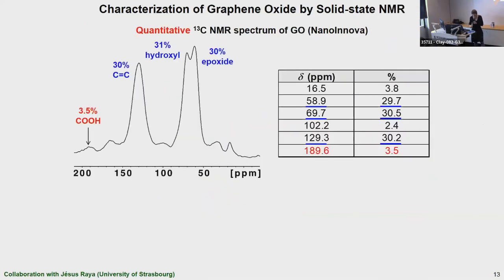We then characterized the graphene oxide by solid state NMR using quantitative carbon-13 NMR. So we could determine that graphene oxide was composed of around 1/3 of epoxides, 1/3 of hydroxyls, and 1/3 of carbon-carbon double bonds. And we could see that there were 3.5% of carboxylic acid, so a very low amount.